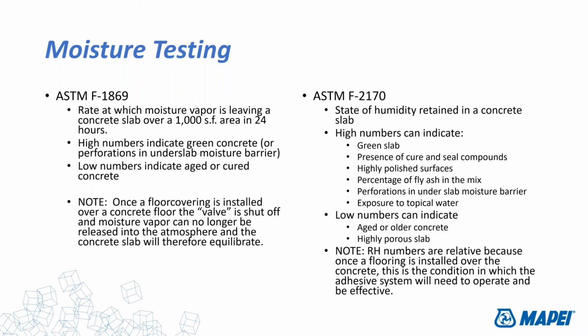Now, the important thing to note about that, in my opinion, is that once you cover it with an impervious floor covering, whether it's carpet tile or sheet vinyl or rubber and so forth, you crimp down the valve on that evaporation rate. So the rate basically goes to zero, and whatever moisture was in there is probably going to still stay there. Yes, you'll get some migration of moisture vapor around seams and cracks or gaps in the flooring installation, but for the most part, you shut the valve on the evaporation rate, and you're left with whatever's left in the slab. And that's kind of what the ASTM F2170 really does. It gives you the state of the humidity, not a rate per se, but the state. What is the condition of the moisture level in that concrete slab?